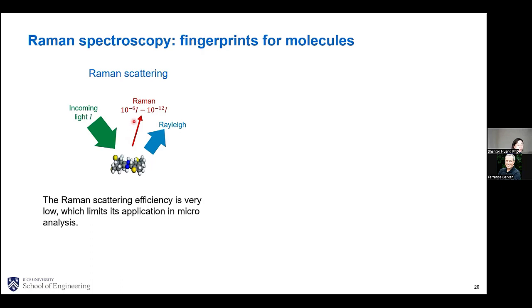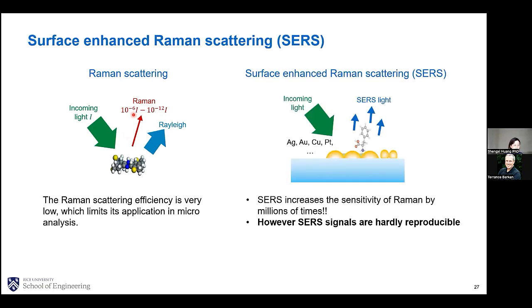The efficiency of Raman is typically below 10 to the minus 6. And that means if you have 1 million photons entering the system, fewer than one of them will undergo this Raman process. So the low Raman efficiency greatly limited its application in microanalysis. About 40 years after the discovery of Raman, a technique called surface enhanced Raman scattering, or SERS, was developed. For SERS, we can use a rough or structured metal surface to plasmonically enhance the Raman signals. And SERS increases the sensitivity of Raman by millions of times. However, a big issue for SERS is that Raman signals are hardly reproducible. And this again poses a great challenge for real biosensing applications.